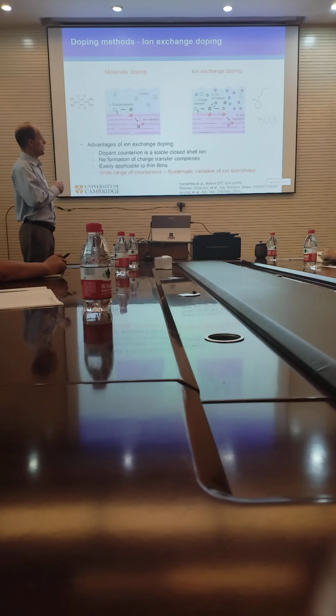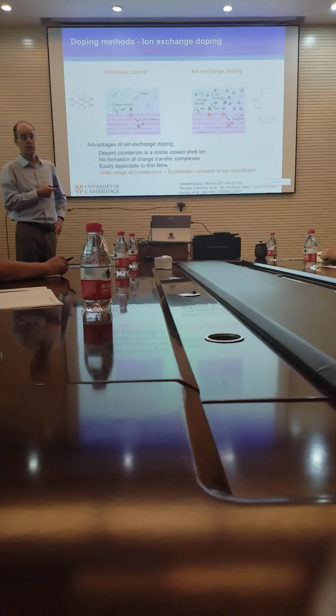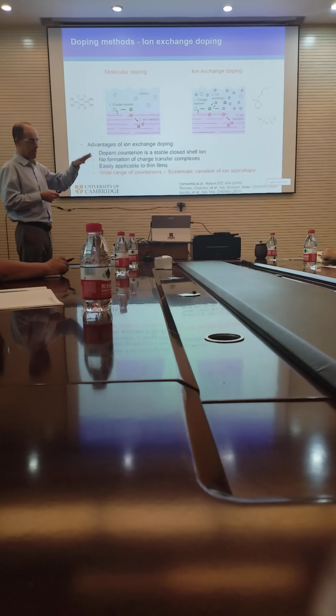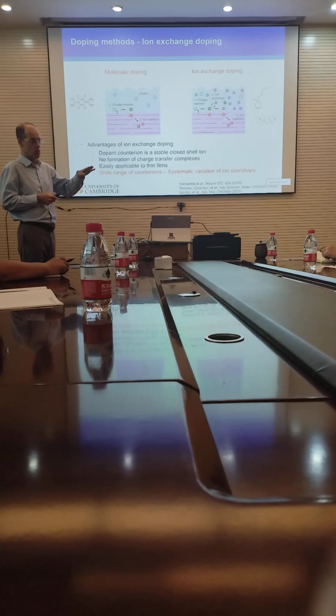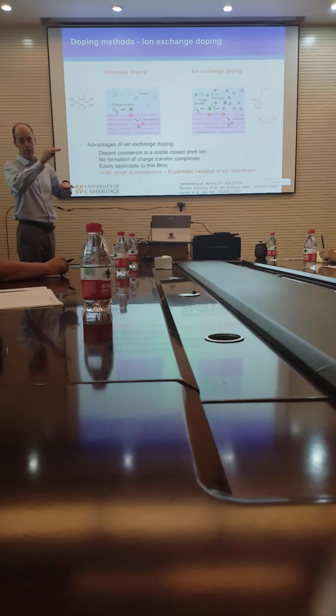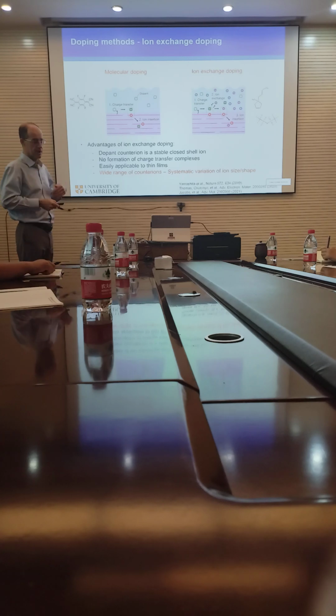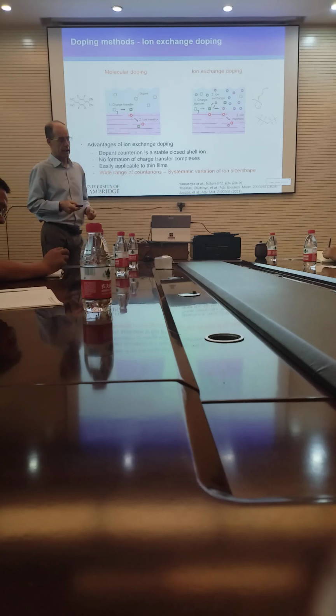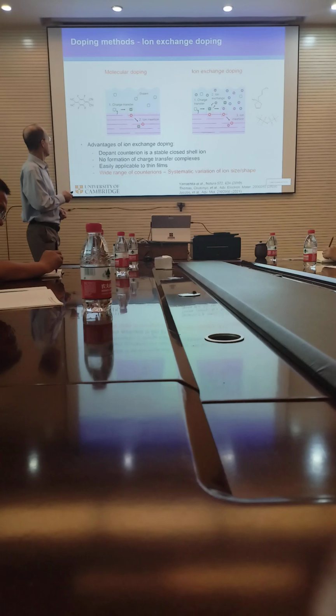You know, in molecular doping, you have this material. If you want to p-type dope an organic semiconductor, you typically use an electronegative molecular dopant that has an empty molecular orbital, a LUMO level that sits below the HOMO level of the material that you want to dope, and then an electron transfer happens from the polymer onto the molecular dopant, and then that's how you achieve p-type doping.